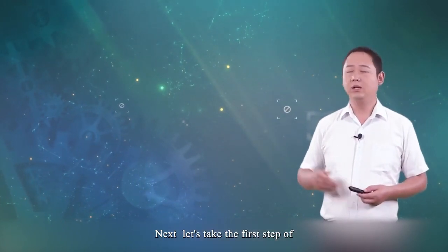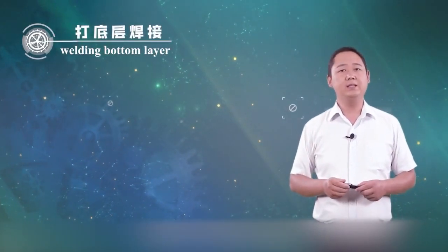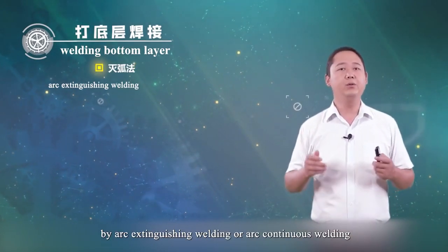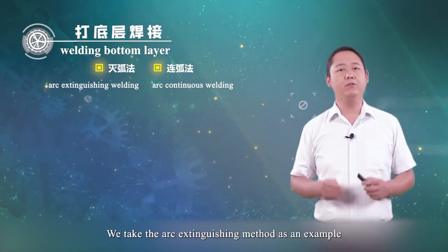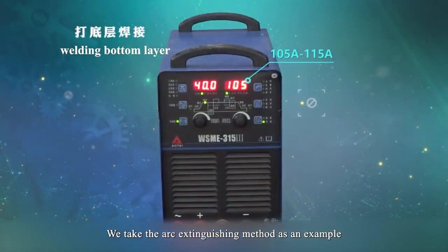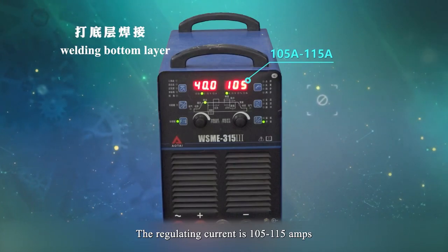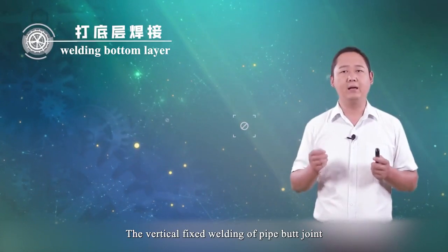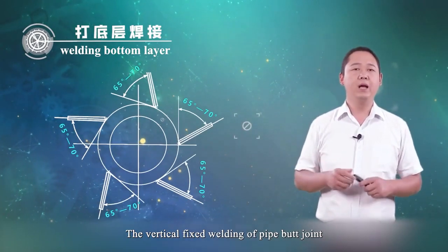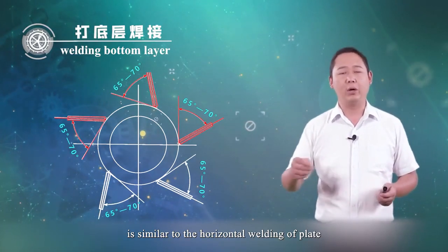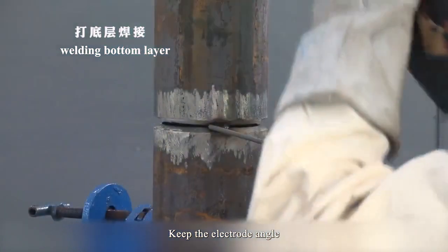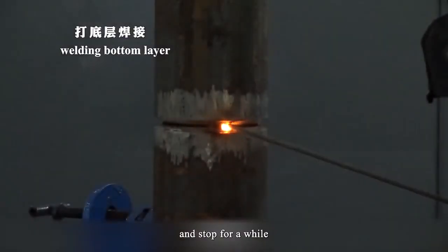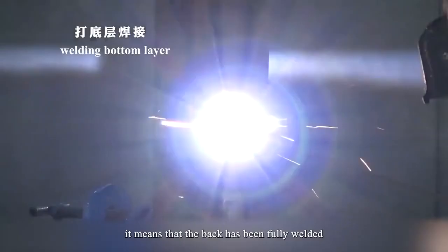Next, let's take the first step, welding the bottom layer. The bottom layer can be welded by the arc extinguishing method or continuous arc welding. We take the arc extinguishing method as the example. The regulating current is 105 to 115 amps. The vertical fixed welding of pipe butt joints is similar to the horizontal welding of plate. Keep the electrode angle. After igniting the arc, lower the arc quickly and stop for a while. After hearing the poof sound from the back, it means that the root has been fully penetrated. Then the arc extinguishing method is used for normal welding.